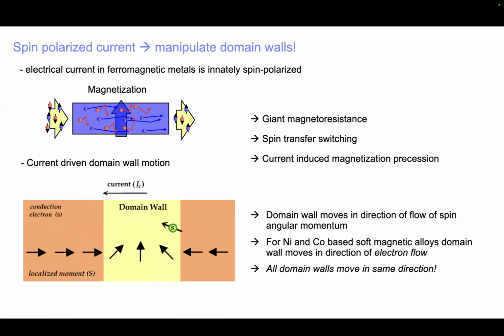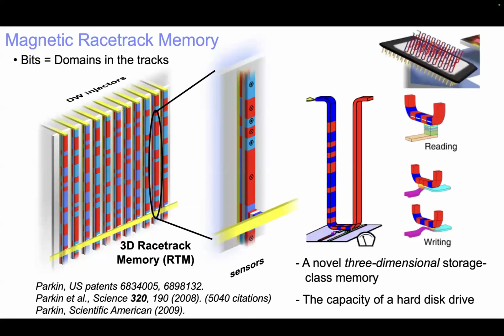This is then the essence of what I proposed as a racetrack memory in 2004. And this is a paper in 2008. We published a paper which is very highly cited, in which I describe this concept of racetrack. And here's the concept shown on the right-hand side. You can see a vertical magnetic nanowire, which is a uniform magnetic wire in which it's magnetized in opposite directions, blue and red. And the information is encoded in the domain walls between these oppositely magnetized regions. So the presence or the absence of a domain wall would correspond to a 0 or a 1.